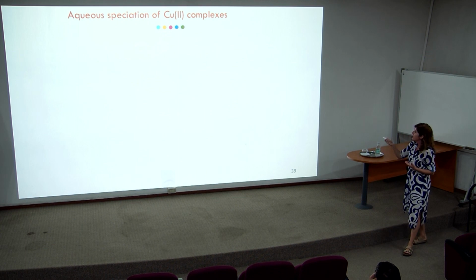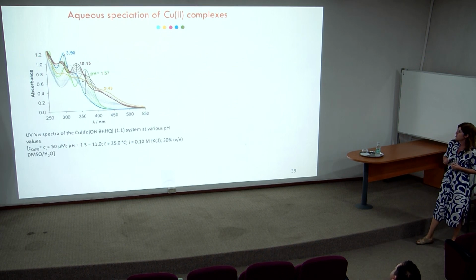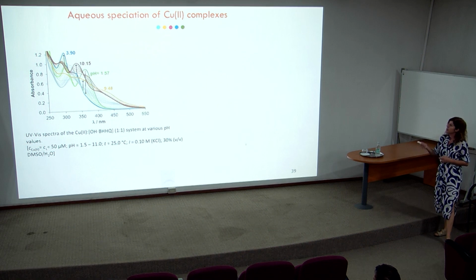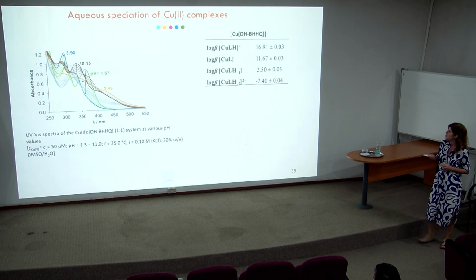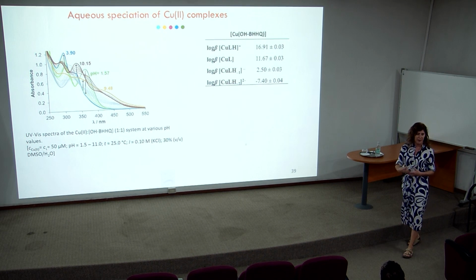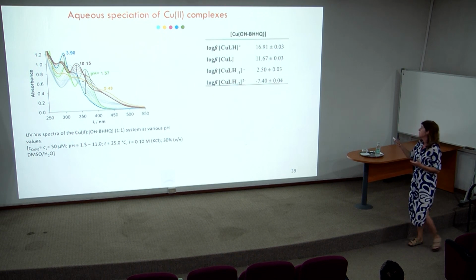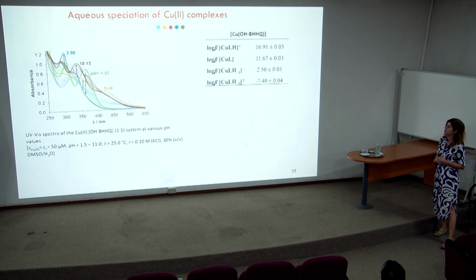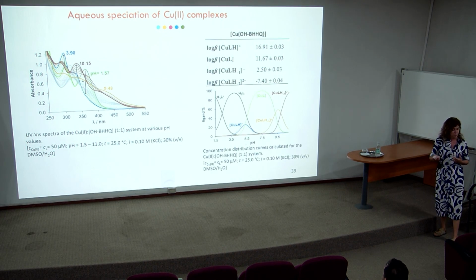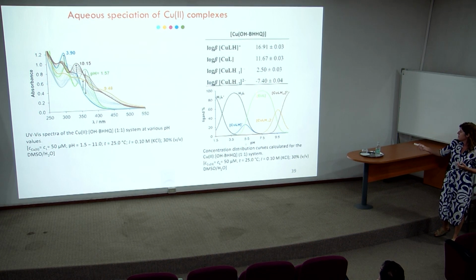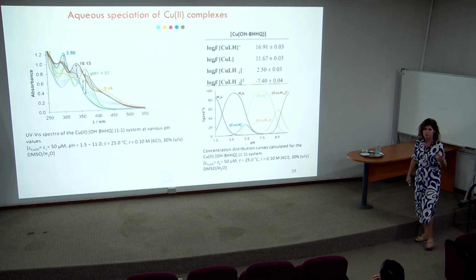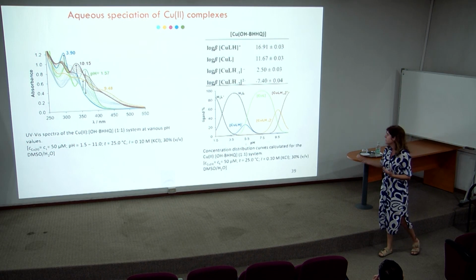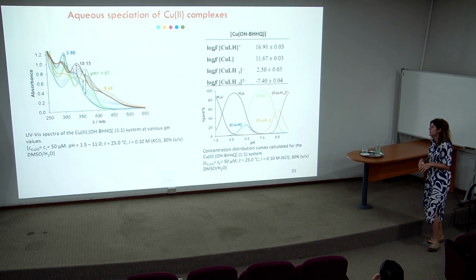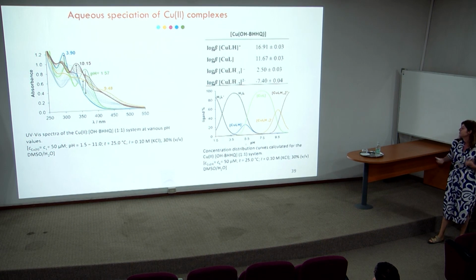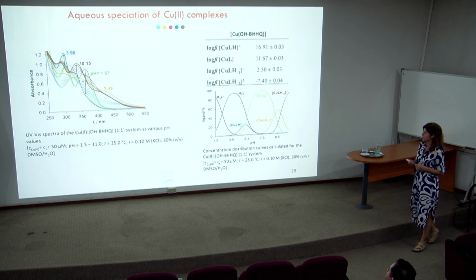We already had the protonation of the ligands, which is essential to characterize the speciation in aqueous solution of the metal species. Again, with spectrophotometry, which yielded the overall binding, the overall stability constants of the different species, which allowed us to model the system in different conditions. And we can see that at physiological pH, we have a neutral copper one-to-one complex with the ligands. So this is one of the systems, but they behave quite similarly, although having different substituents.